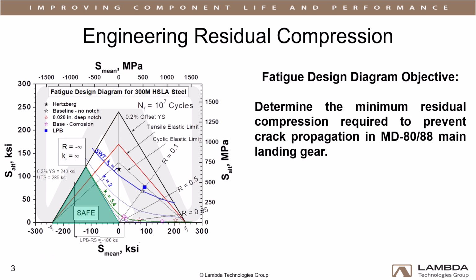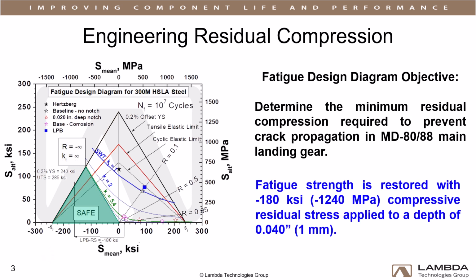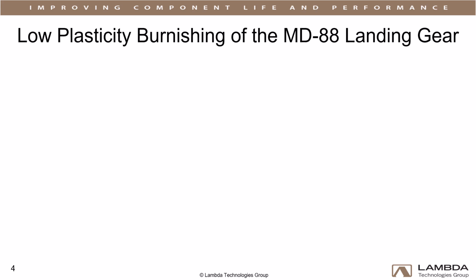When the fracture-prone region is in a fully compressed state, the tensile stresses are absent, and therefore cracks cannot initiate or propagate. In the MD-88 landing gear example, compression of -180 ksi was applied to a depth of 40 thousandths of an inch to restore nominal fatigue strength to the damaged surface. A request for an alternative means of compliance, or AMOC, was submitted to the FAA with detailed plans for testing and implementation. Once the engineered residual stress field is designed, the next step is processing the component.